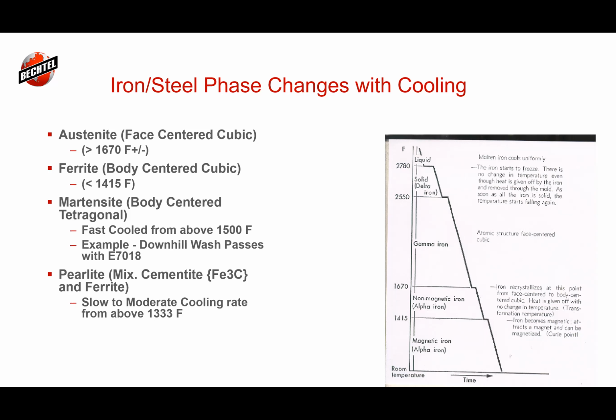It's kind of like if we can cool the steel down nice and slow from austenite down to ferrite, it's going to rearrange itself. And it's going to go from austenite to ferrite. If we quench it and we lock it in, it's going to go to martensite. And martensite is very hard. It is a different arrangement. It's called body center tetragonal, and it might not be the happiest or the most equilibrium. That's where the party analogy comes in.